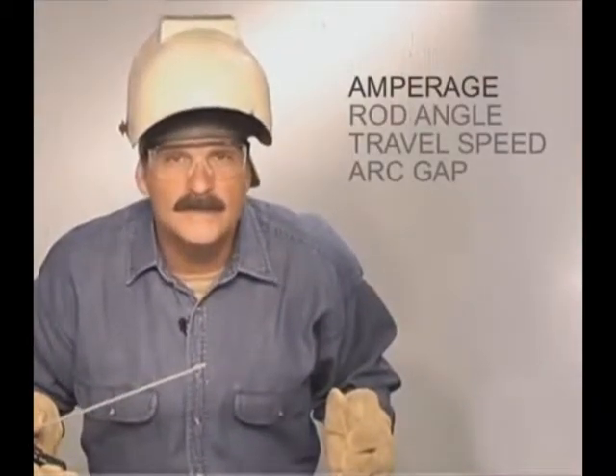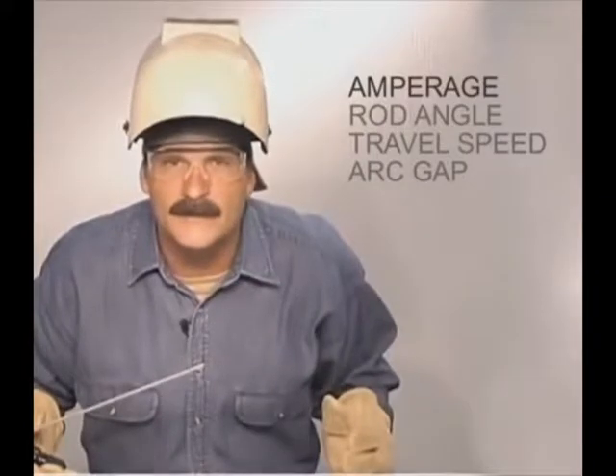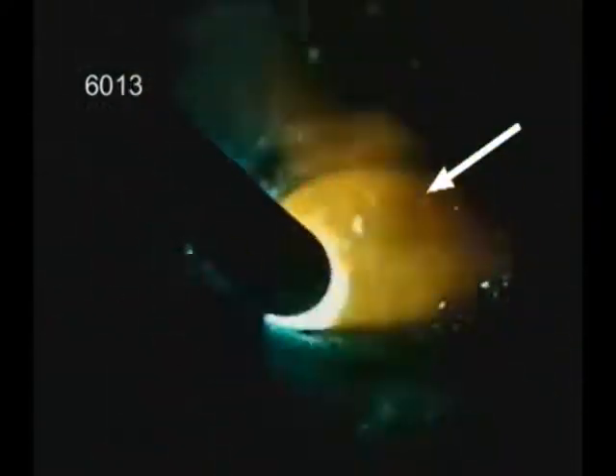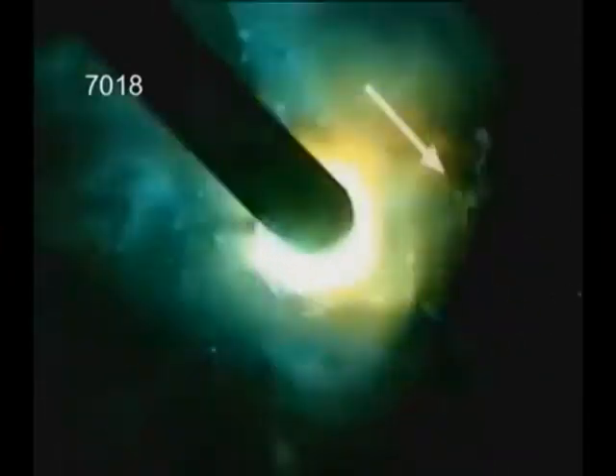Because of the characteristics of the flux coating, the puddle will look different depending on the type of rod you're using. The entire puddle is visible with 6010 or 6011. Slag covers the top rim of 6013, but the molten metal is still visible on the sides, and the puddle should move easily with the rod. With 7018, slag covers the entire puddle, but you still want to see it flowing out to the sides, with the slag solidifying back from the rod. During the weld, the filler metal is actually solidifying underneath while the slag stays molten.